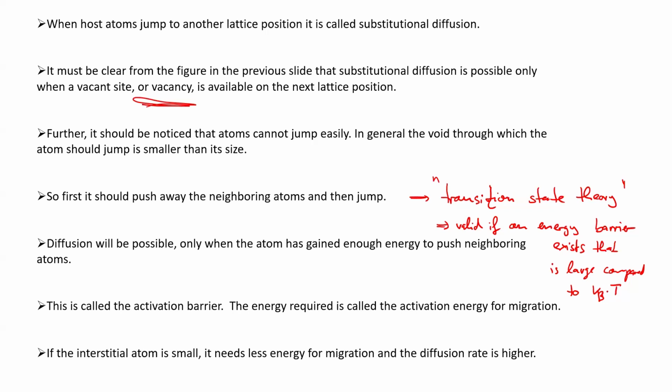If an energy barrier for any process is small compared to kBT, the statistics describing any type of reaction occurring means that you are in the fluctuation regime, meaning that the reaction can take place any time. Any oscillation, any excursion of the system might actually go to the new state. In this case, diffusion, it means the hop, the jump can take place.